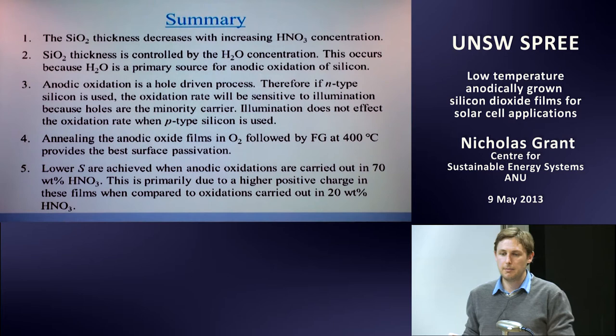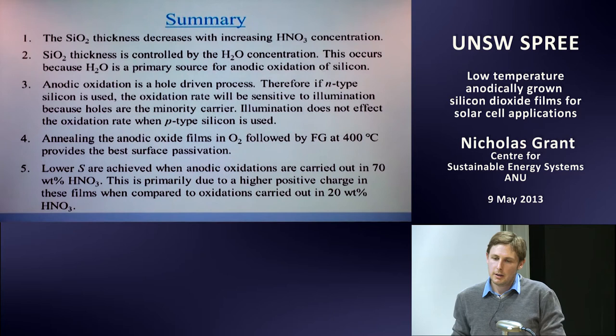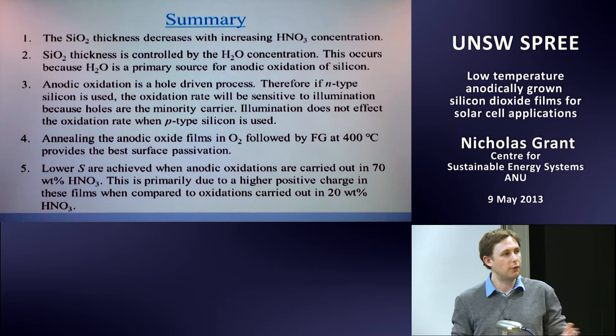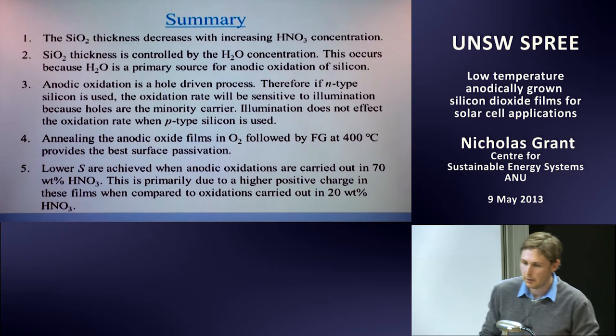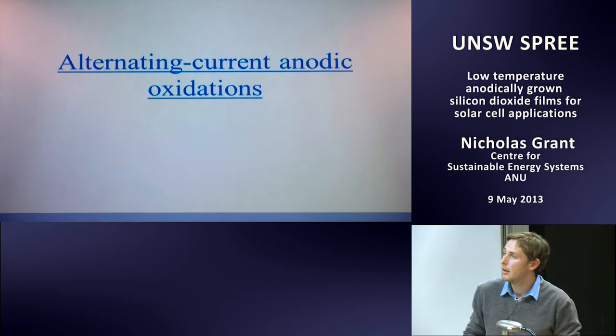Summary of the DC section: Silicon dioxide thickness decreases with increasing nitric acid concentration, controlled by water concentration. Anodic oxidation is a hole-driven process, so illumination greatly affects the oxidation rate on n-type silicon but not on p-type. Annealing in oxygen then forming gas at 400 degrees provides the best surface passivation. The lowest surface recombination is achieved with oxides grown in 70% nitric acid, because these films contain a high positive charge.